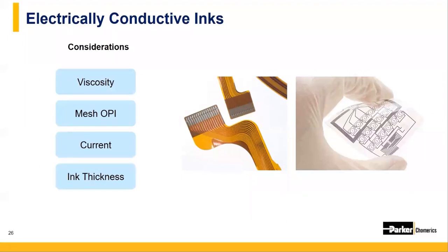When screen printing conductive inks, pitch and thickness of the printed lines will vary, and the mesh screen openings per inch will depend on the conductive filler particle size. So you want those little flakes to make it through the screen and onto your substrate. In addition, you also want to consider whether those printed electrodes will be coated with or applied onto a dielectric or insulating material.